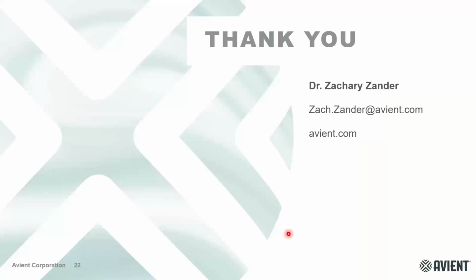Thank you. And this will be our last question. How does the process temperature compare to PC? So the processing temperatures, that's a good question. The processing temperature for this material is a bit lower than PC. So generally speaking, when we injection mold these, we try to target a temperature of about 230 to 240 degrees centigrade, whereas for, let's say, a PC alloy, you might be closer to 280 to 300 degrees centigrade. So it is a bit lower in terms of its processing temperature.